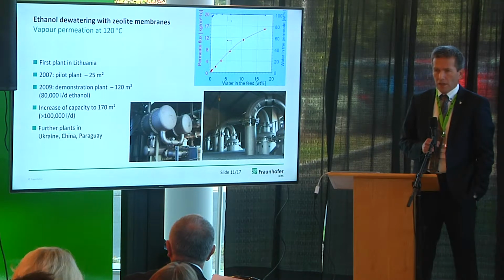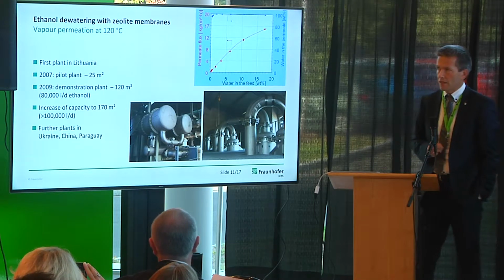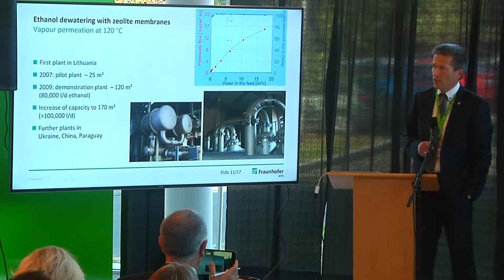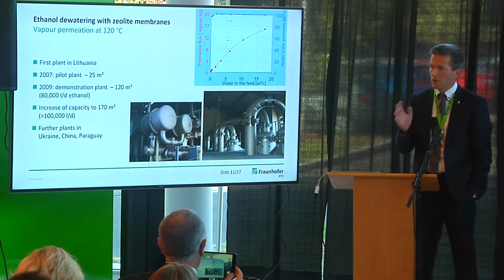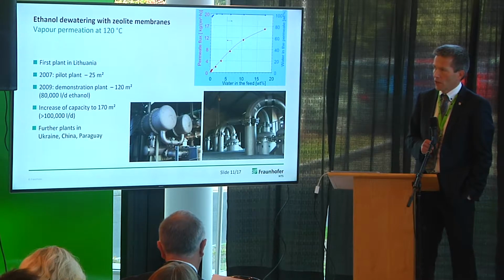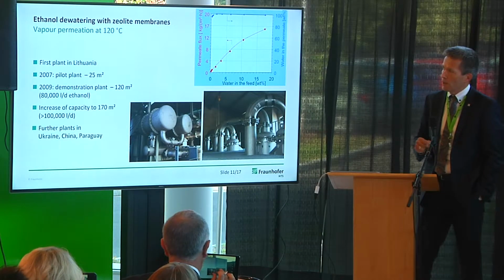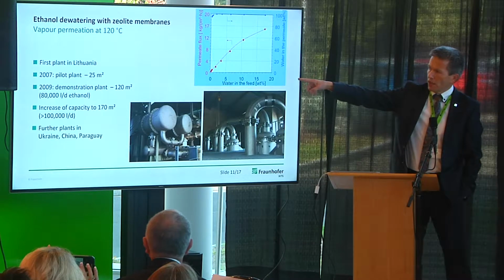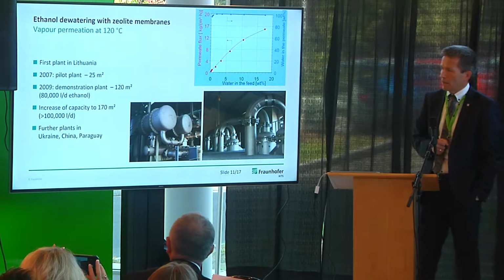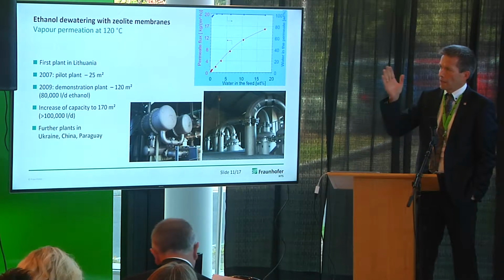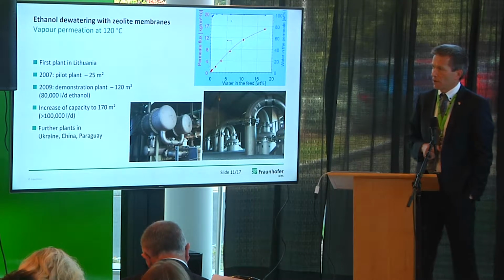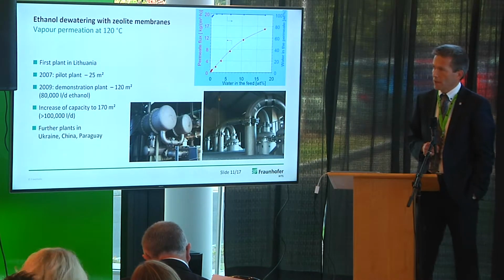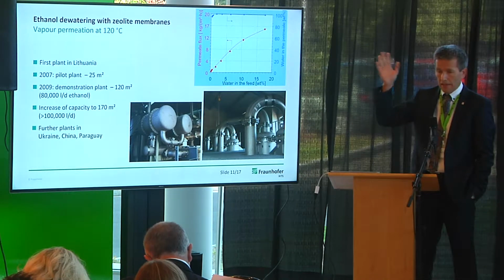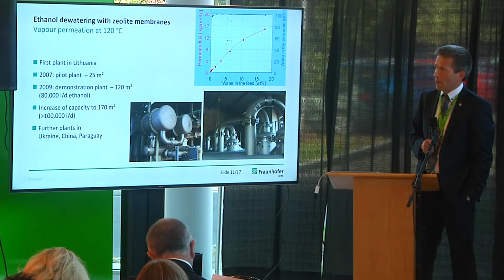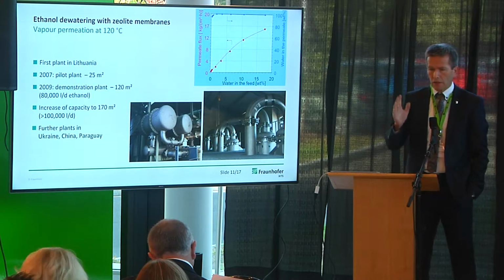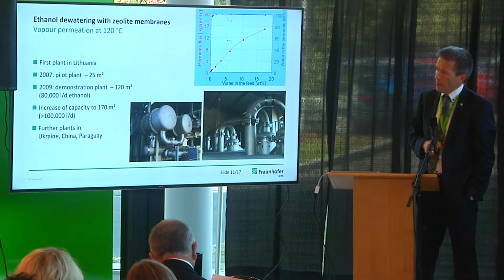Well, next example is also with the zeolite A membrane. It is pervaporation or vapor permeation, in this particular case with zeolite A membranes, for the dehydration of bioethanol. So the membrane, this is well known, has a very good performance. If you start with 10% water in ethanol at 120 degrees C, you get a flux of nearly 12 kilograms per square meter an hour, and a very huge selectivity of 2,000, 3,000.